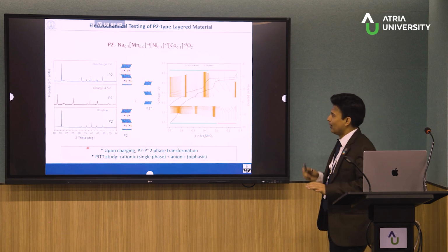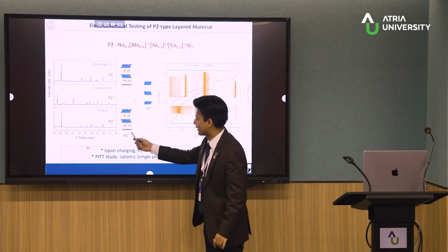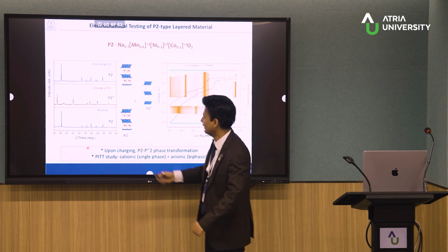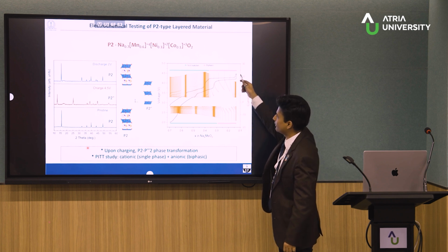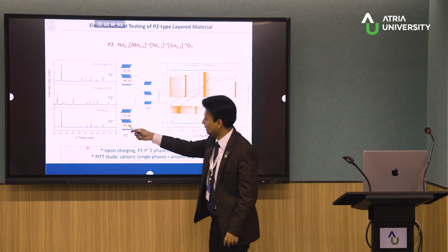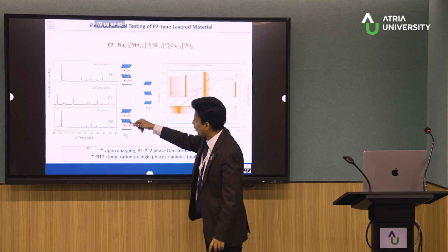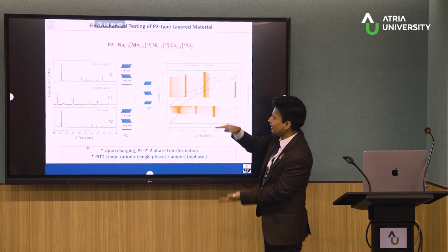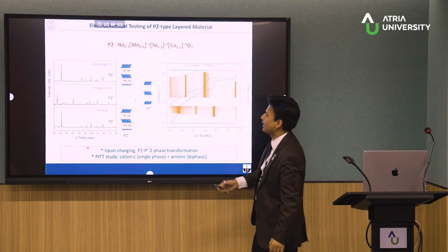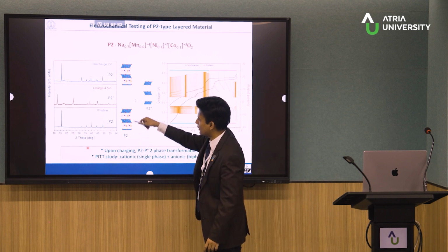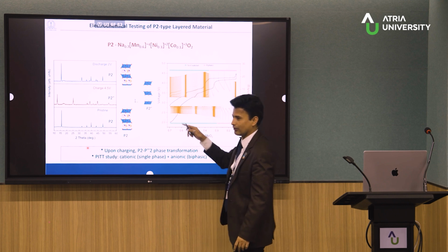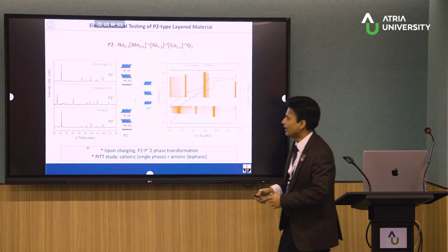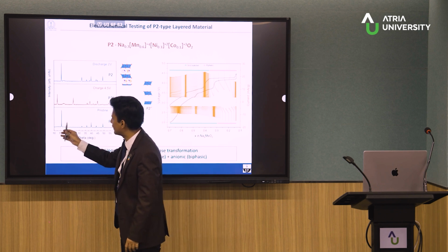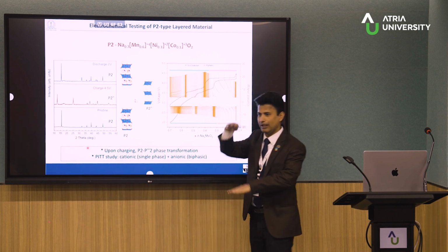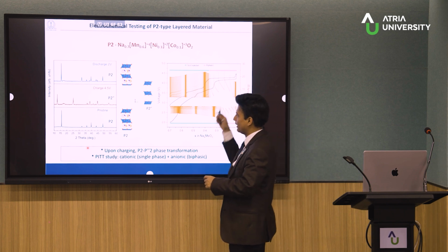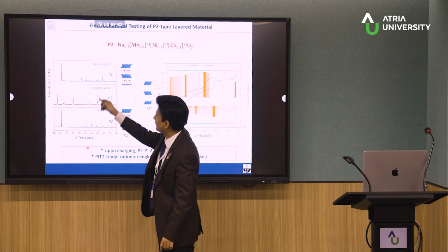Now, what happens when we have this material? This is a P2 kind of system, as I mentioned. This is the initial pristine material, and when we charge to very high voltage, then what happens? All the sodium go out, and because of that, the oxygen has a huge coulombic repulsion, and the interlayer distance increases, and it remains P2, but because of the huge change, we can call it something called OP4-like, a distorted version of P2, and as a result, you can see the peak shifts towards the lower angle. Lower angle basically means high interplanar distance, and when the sodium comes back again it goes back to the similar P2 structure.